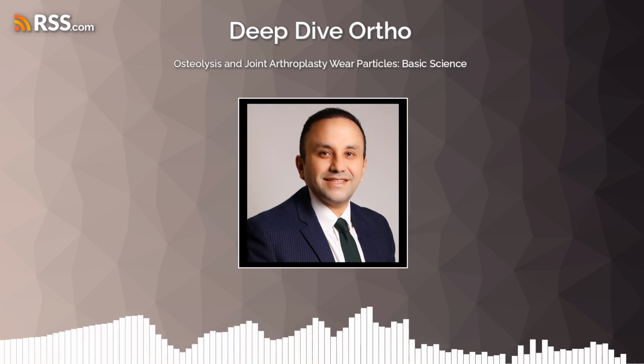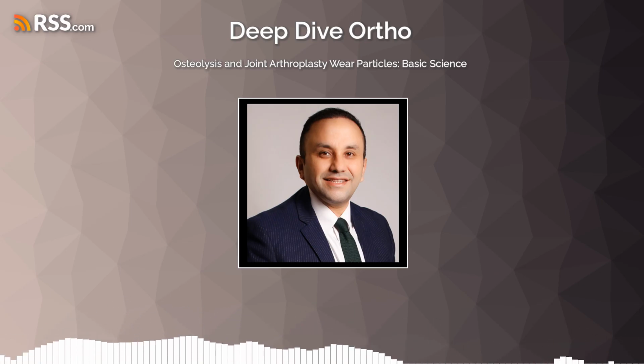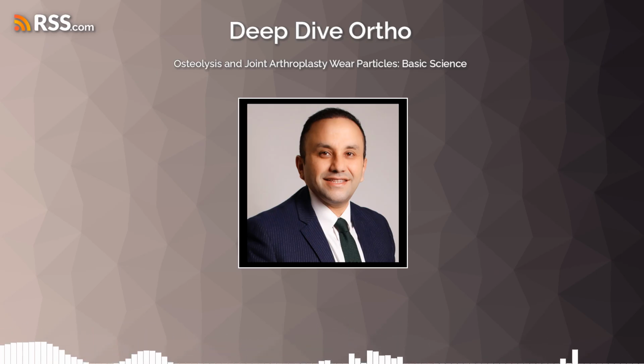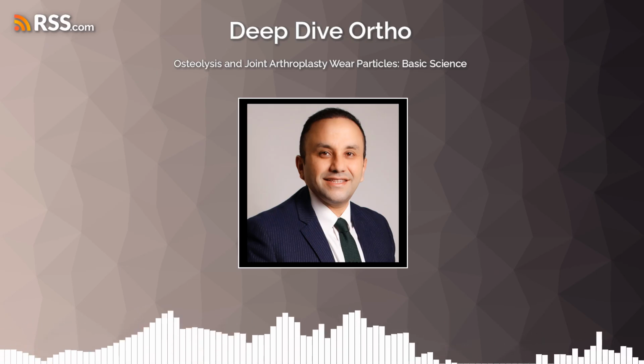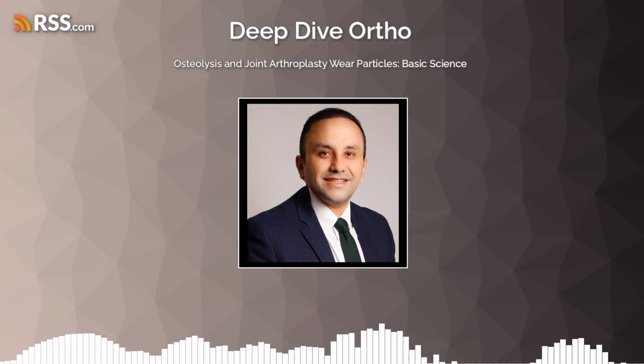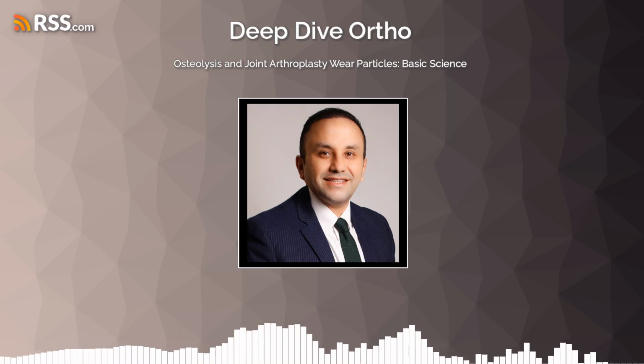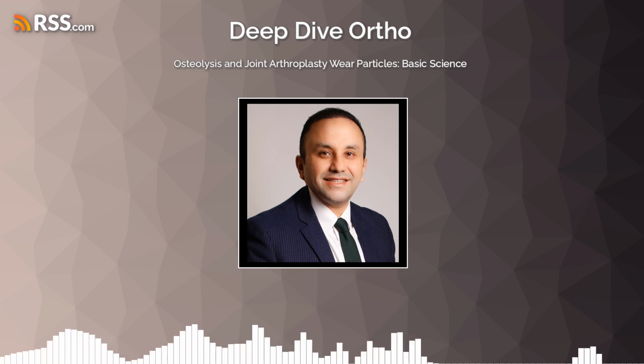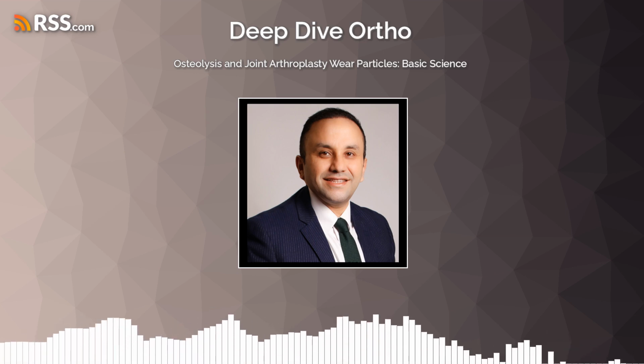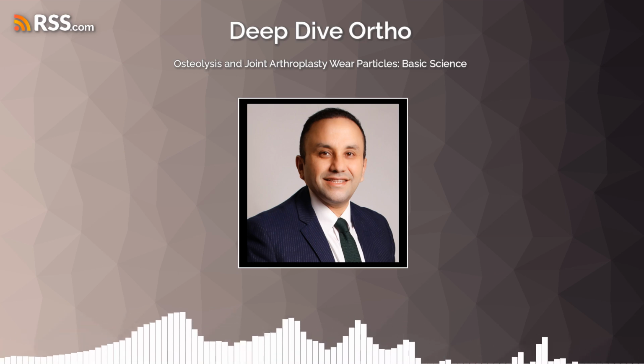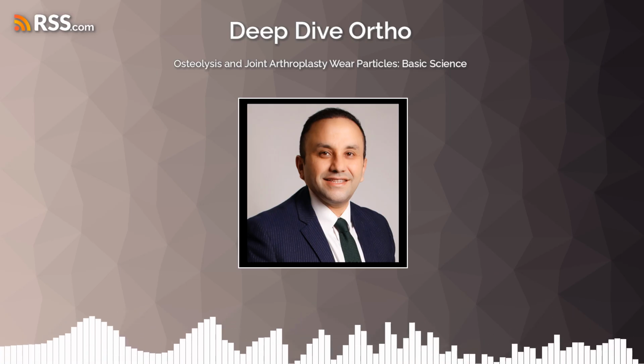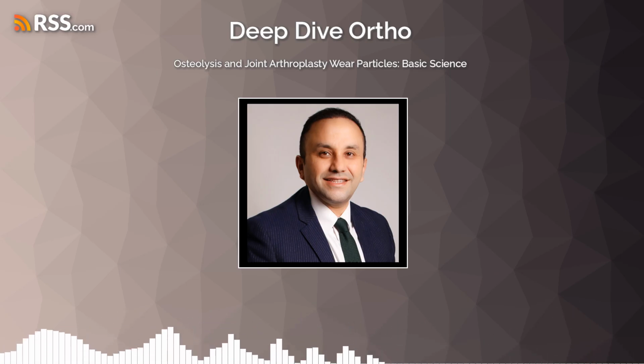Initially, yes. However, titanium, when used for bearing surfaces as opposed to structural components like stems, has historically shown a high failure rate due to its poor resistance to wear and notch sensitivity. It's prone to cracking. Right. But what's particularly significant and, well, concerning with metal-on-metal wear is its tendency to stimulate lymphocytes, leading to a more pronounced and widespread lymphocytic reaction in the surrounding tissues.